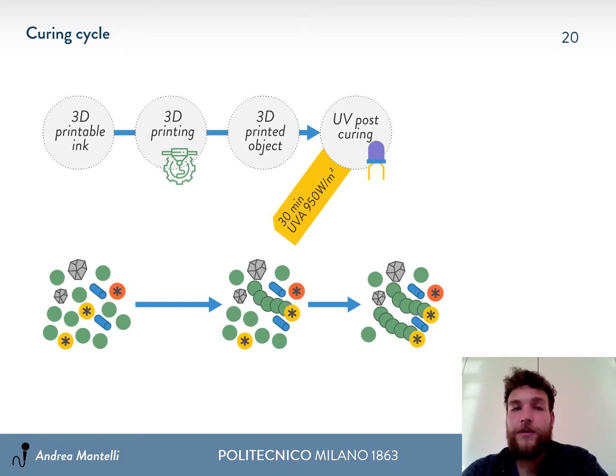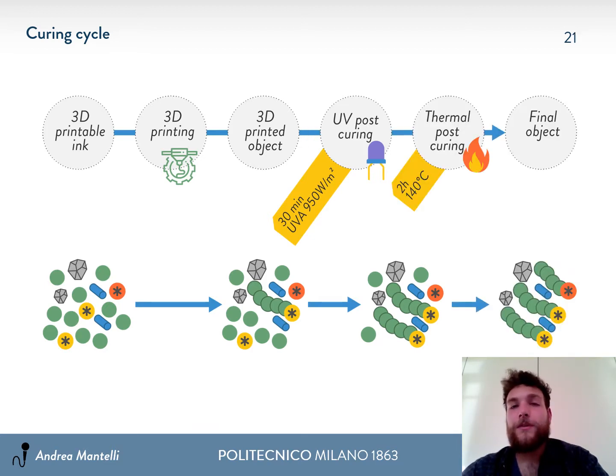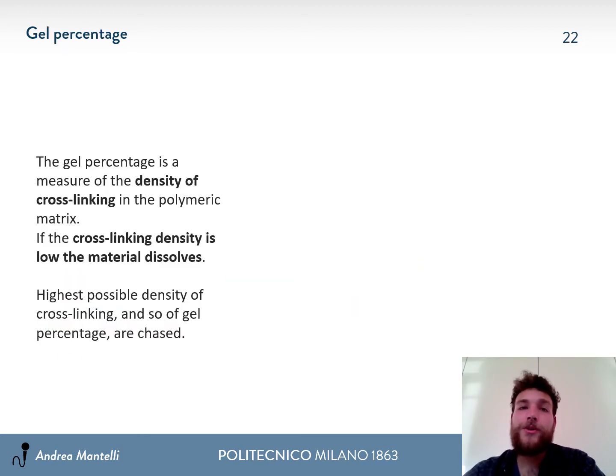Then, with a UV post-curing, we ensure that all the photoactivity of the resin is extinguished. And then with the thermal post-curing, we complete the cross-linking of the matrix. In order to be sure that all the material was cross-linked, we also performed a gel percentage test, and the higher the gel percentage, the higher the cross-linking density, and so the lower the unreacted monomer.